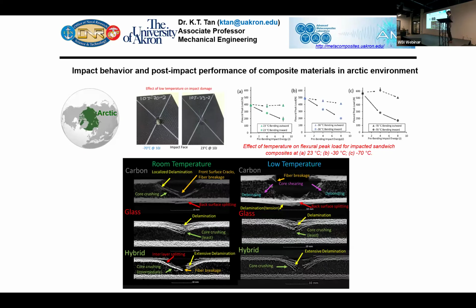Now, if we go from high temperature down to low temperature, Professor K.T. Tan in mechanical engineering is looking at multi-layer composites in Arctic applications, where they do their testing at minus 70 degrees. Under those conditions, virtually any polymer composite is going to be in a glassy state. It has a completely different fracture and failure mechanism. What they're excellent at is performing the lamination and the testing of these materials. They produce what are called sandwich composites, a combination of carbon fiber and glass fiber composites. And they've done a lot of work characterizing how these materials fail and delaminate when you go to these extreme cold conditions.